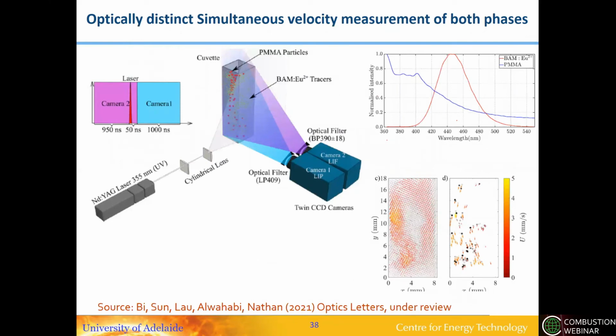One of the other measurement methods we've been developing to assist with measurements in these particle flow reactors is a method to give optically distinct detection of both a tracer phase and a particle phase. Here we did it for research using a polymer, PMMA, which is a spherical polymer particle, and the BAM tracer, which is typically used for phosphor thermometry. These two methods together can be driven at the same wavelength but emit at different time scales and also different wavelengths, which allows them to be discriminated optically.